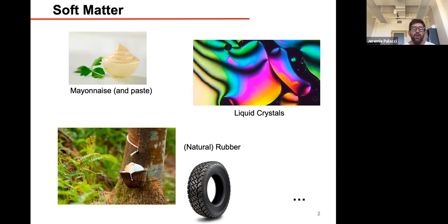And so that highlights two essential components of soft matter. First, it's going to go under drastic changes with mild modification. So here you have a chemical reaction which can happen at room temperature, and that's enough to turn the polymer chain into a network. And importantly, instead of having molecules, you add to your system an intermediate scale, which is a mesoscopic scale, where those different chains would form a network, and that's essential to soft matter.